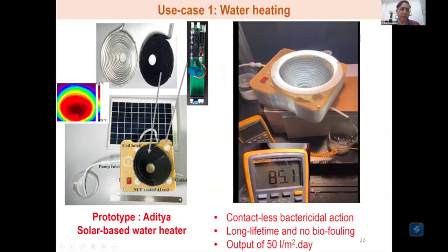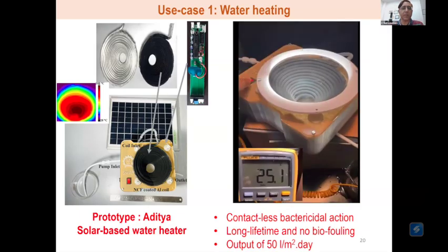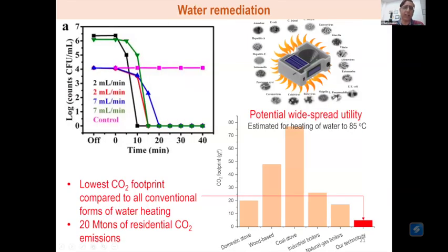A device like this, which is hardly 1 foot by 1 foot and weighs about half a kg, can give you an output of 50 liters of water per day. And basically, this is again zero cost heating. And what we did was, if it crosses 80 degrees, that means we can get rid of biological material. We can get rid of pathogens.